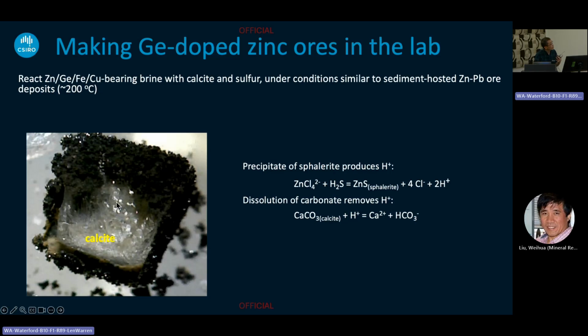So this is the product from our experiment. You can see this fluid, after reaction with calcite, is precipitating from the surface by replacing calcite. So that's the first step. What it really indicates is the precipitation of sphalerite by reacting zinc chloride with sulfide to form sphalerite. But it also releases protons into the water, making the fluid more acidic.